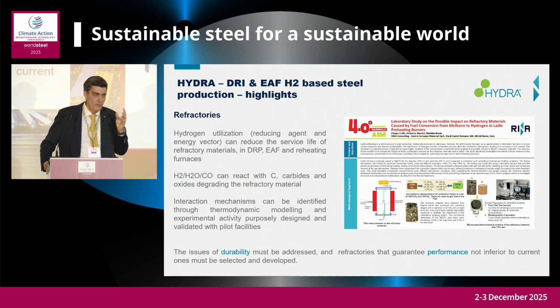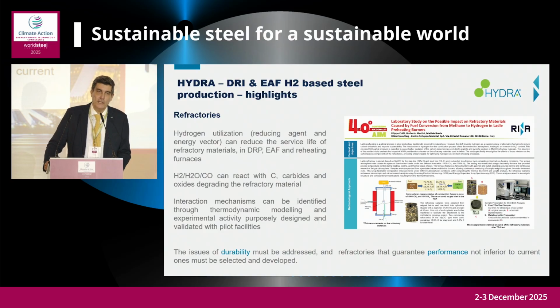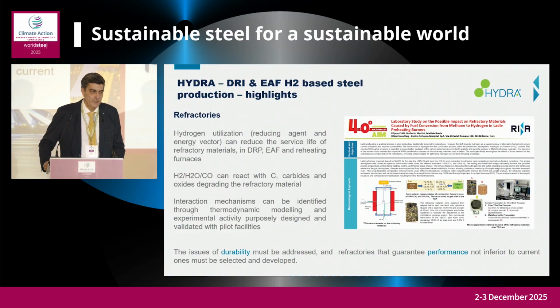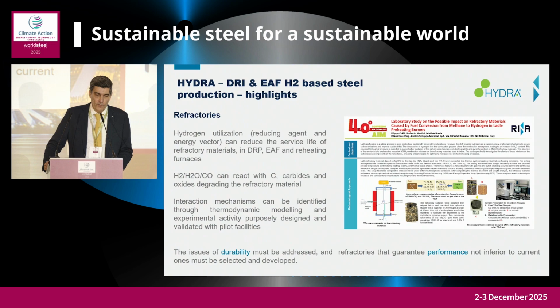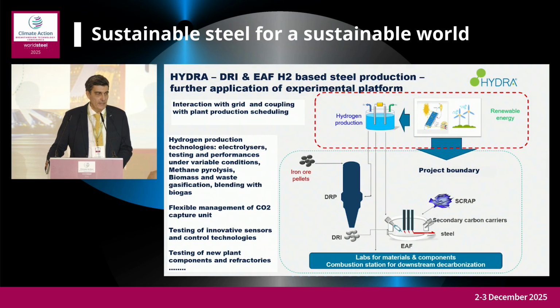This is another example about materials, focused on refractories, which is the impact of hydrogen or water on the refractory durability. Here we performed some tests with magnesia refractory for the ladle. In this case, the topic was ladle preheating, and we see that at the ladle preheating temperature there is an interaction, but it is meaningful from the practical point of view. Those types of study should also be repeated for other types of refractory. For the moment, we don't yet have the experimental facility, so we perform simulations with a calculation code, making some hypotheses about the interaction. So we have some reaction scheme in mind, and we have to check it by experimental activities. At the end, a further possibility of the experimental facility.